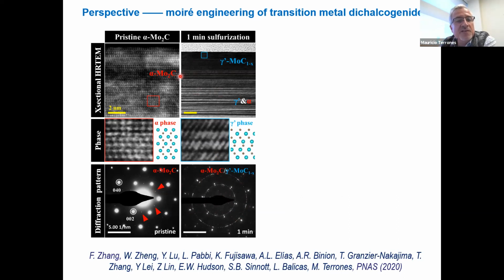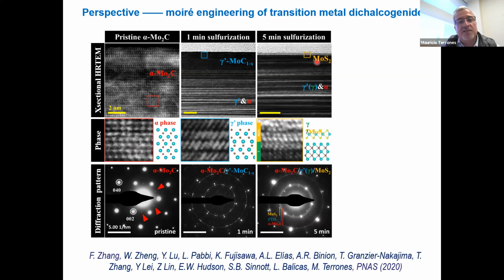And what you see here is that you have these sort of layered structures, and one of them is the gamma prime moly carbide, and then you start to see the alpha moly carbide. So we start from the edges, with the sulfur. The H2S helps us start transforming the alpha moly carbide into the strained phase of gamma prime moly carbide, and you don't have any moly sulfide growth yet. After 5 minutes, you can start seeing some moly sulfide, and you have here 3 rings, right? Which tells you that you have the alpha moly carbide, the gamma prime moly carbide, and the moly sulfide. So you have all of them coexisting.